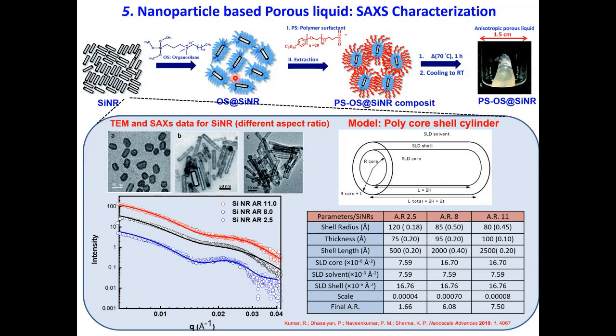But we work with porosities which are in nanometer scale. So these are silica nanorods which are actually hollow. SINR stands for silica nanorods, and we can coat these rods with polymer, and since these are hollow, once we coat them with polymer, they form a system which is actually liquid at room temperature, and we can start pushing gases into these hollow cores.